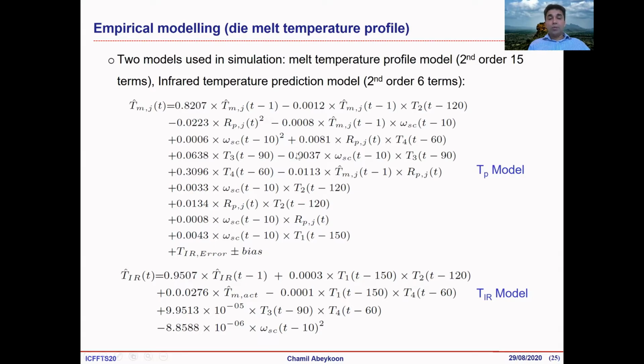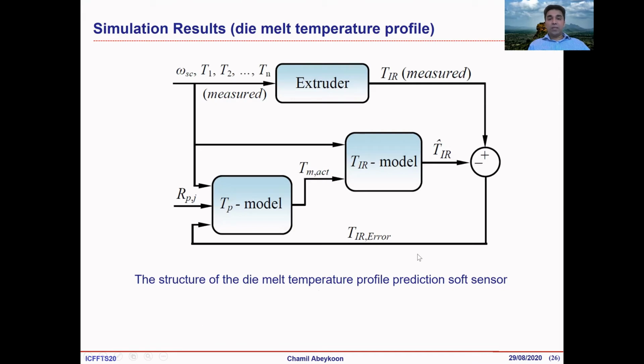In the soft sensor, we need two main models, the TP model and the TIR model. The TP model predicts the melt temperature at different locations. The TIR model predicts the melt temperature measured by an infrared sensor, and we're going to use this as a feedback model. So this is the structure now. In our soft sensor, this is the extruder, and we have process inputs. We're going to measure them, and those are the inputs to our models.